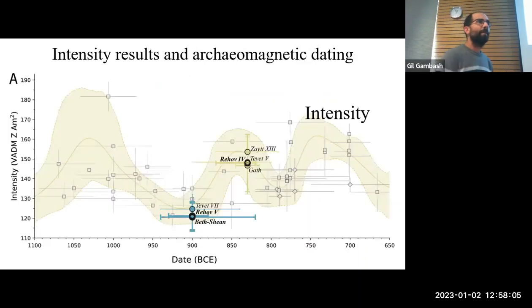Moving on to the intensity, here it's an even clearer picture. You see again, Beit She'an is down here, with much lower intensity, then Rehov 4, Gath, Tevet, and here we have also Tel Zayit, where we didn't have direction results, but only intensity. But again, a good agreement with Tel Zayit 13, which is also attributed to Hazael. All these agree with each other, but don't agree with these three. Here we have Beit She'an, Rehov 5, the apiary. As I said, we didn't have anything in situ, so we didn't have directions, but we had intensity, just the beehives themselves that were burned, and Tevet 7.